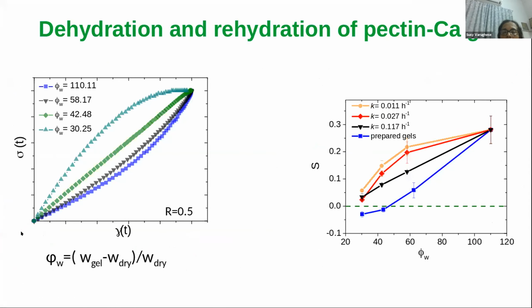As I said, it also has implications in dehydration and rehydration of pectin calcium gel. We did some experiments with the same gels with R equal to 0.5, which means it has the egg box bundle structures and also has strain stiffening characteristics. This is taking the gel and allowing it to dehydrate at different rates, to understand how it behaves, and then rehydrating them.